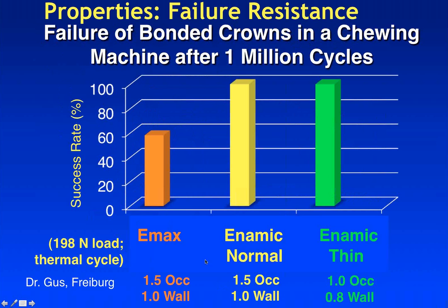Now, the really interesting study that we didn't do and VITA didn't do, they contracted this out to Dr. Gus at Freiburg, and this was a chewing machine test in which the crowns were made at different thicknesses. They were bonded onto a substructure, again, that has the same properties as dentin, and they were placed in water. They were thermal cycled between 5 degrees C and 55 degrees C, so you get a very big change in temperature. You're also chewing on it with almost a 200 Newton load, which is a very high chewing load, and ran this for about 1 million cycles. And they like to do millions of cycles over in Europe.